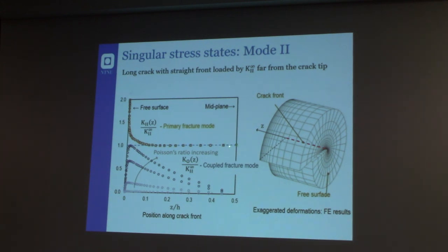because applying a remote stress intensity factor of mode 2 equal to this, close to the free surface of the plate, sorry, at the tip of the crack close to the free surface of the plate, we have a value which is very close to the maximum value that we are applying nominally. So this effect is not negligible. Actually, this explains many failures that we have from the free surface of three-dimensional components that are not easy to explain if you consider two-dimensional models. So this was a very good scientific achievement.